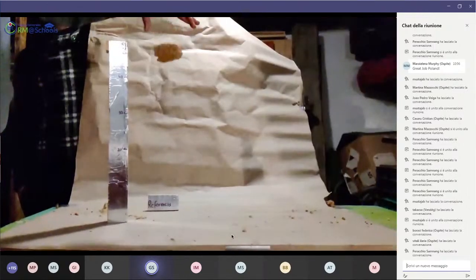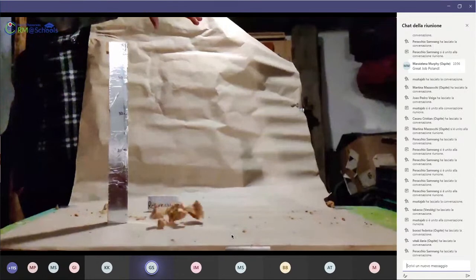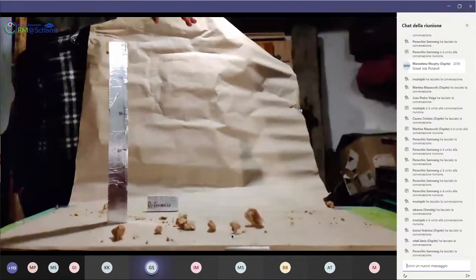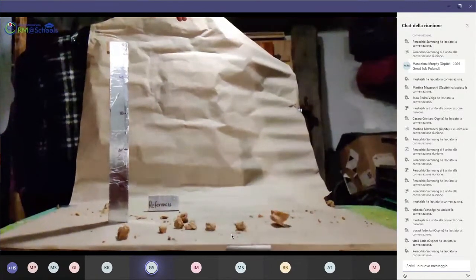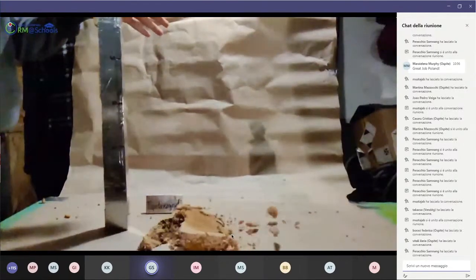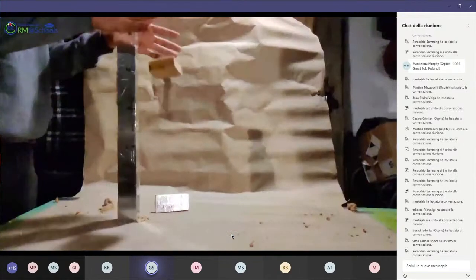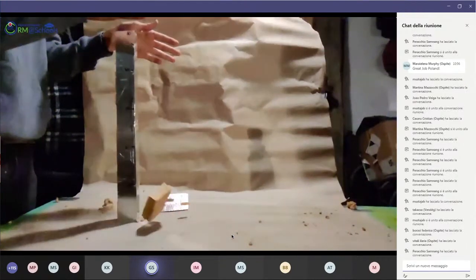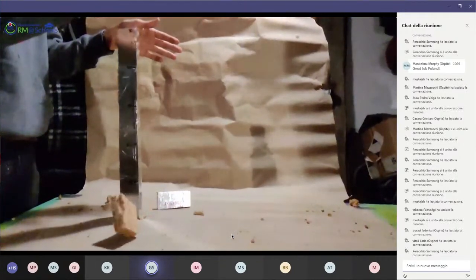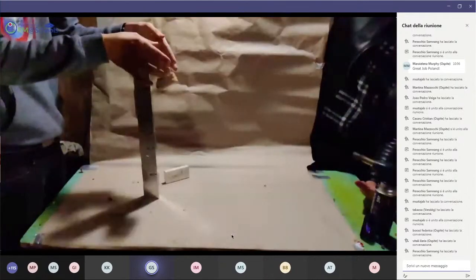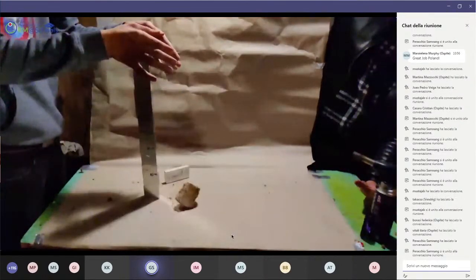Our second experiment was a dropping test from 15 centimeters. The referential slab fell apart, it didn't pass the test. The wallpaper glue slab remained mostly intact, with only a larger piece falling off. The polystyrene slab behaved as expected and stayed intact. The cement slab passed the test well and stayed in one piece.